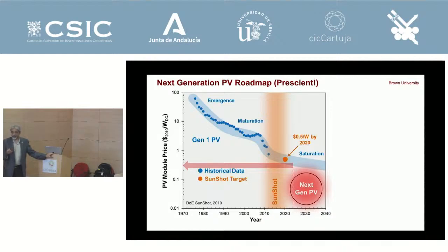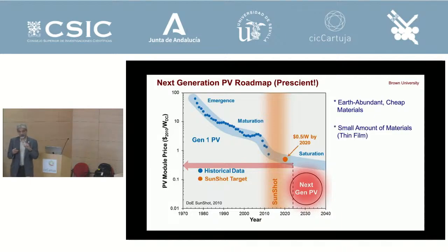And so in order to get there, you have to have earth abundant materials in this solar cell. You cannot have precious metals, otherwise you cannot decrease the cost. You have to have small amounts of material. You cannot have large wafers or bulk materials. You have to use minimum amount of material, even if it's earth abundant. Cheap to make. Solar silicon is basically melted. The melting point of silicon is 1425, so it has to be molten at 1600 degrees Celsius and cast into single crystals, right? So there's a lot of energy that goes into it. There's a big carbon footprint.